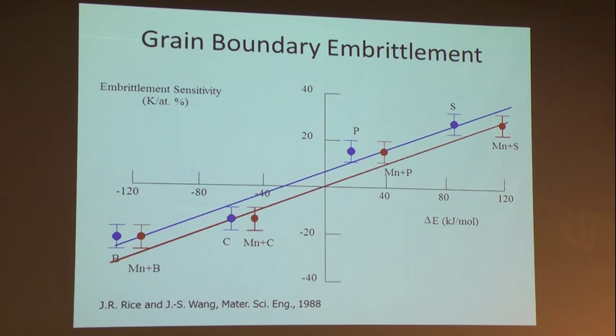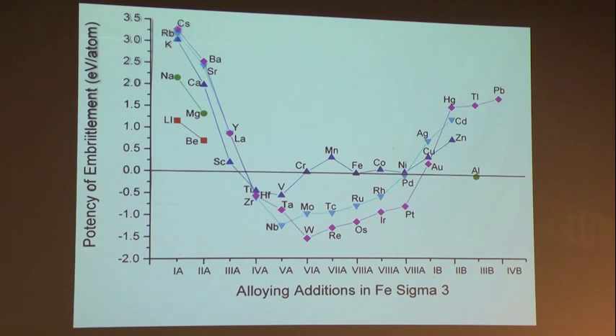Now, less well known at the time was the role of the substitutional alloying elements. So the same methods were used to predict the effects of substitutional elements for a handful of cases with the rigorous calculations, used that to calibrate a simplified model that then made the projections here, allowing us to identify the largest negative numbers, which are the strongest substitutional cohesion enhancers. This was then validated with the more rigorous calculations.